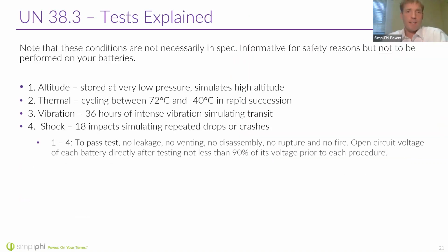And so what goes into these tests? I'm not going to spend a lot of time talking about it. I gave you a rough idea of what happens. So again, when you get on an airline, especially your checked baggage, it ends up in a non-pressurized environment in the cargo hold of the plane. And so altitudes have low pressure, low temperature. And so part of the UN 38.3 is a test to simulate that cycling of pressure. And then thermal, there's also a cycling of the temperature, right? You're going from 72 Celsius, a very hot temperature that you typically wouldn't experience, but a hot temperature down to a really low temperature. And we're doing these rapid cyclings in these tests. Again, SimpliPhi has passed these tests.